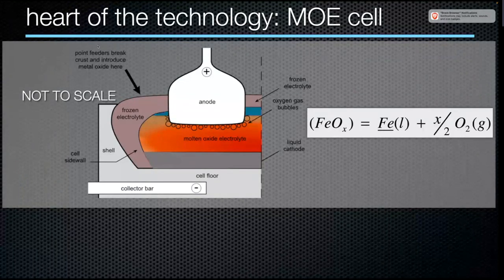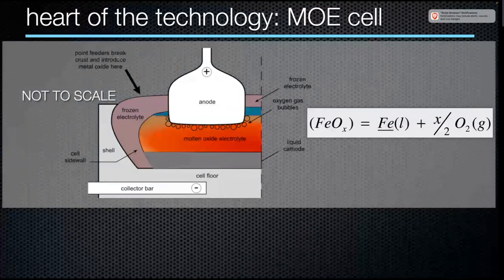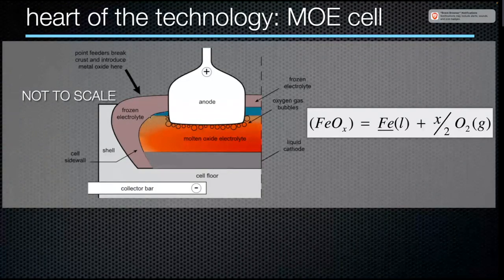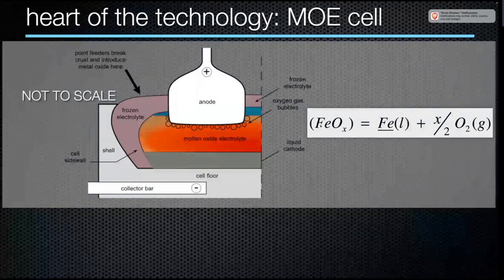And so starting up here in the upper left, we introduce the oxide, whether it's hematite or magnetite, and it dissolves into the molten oxide solvent. And then by the action of electric current, we send current from the anode to the cathode, and we break apart. We see here the equation on the right. So it's FeOx, whether it's Fe2O3 or Fe3O4. By the action of electric current, this is decomposed into Fe, pure liquid, and O becomes O2 gas.